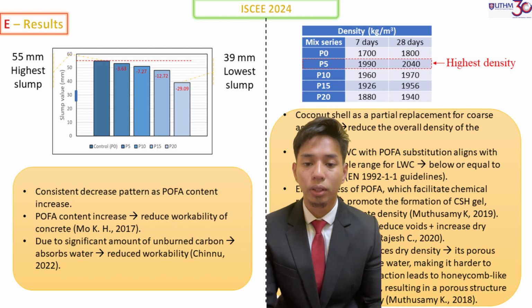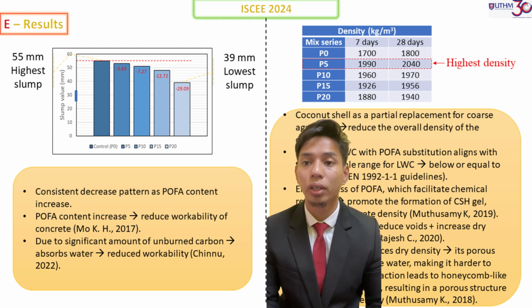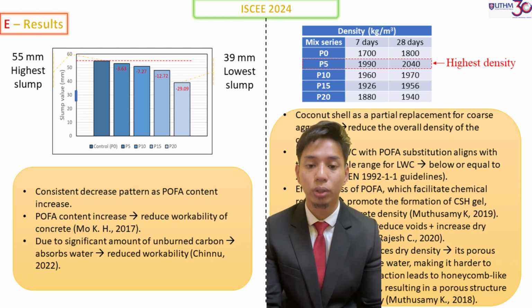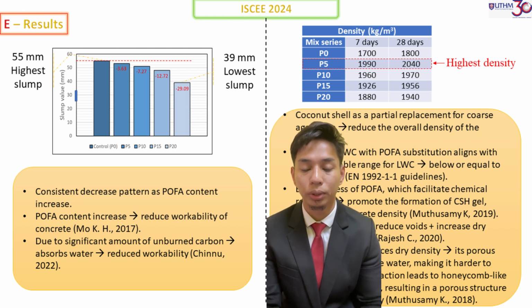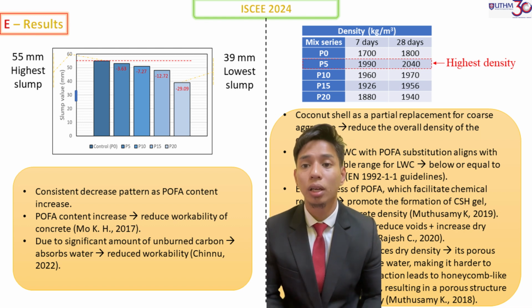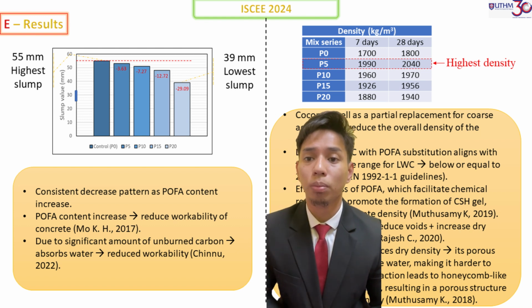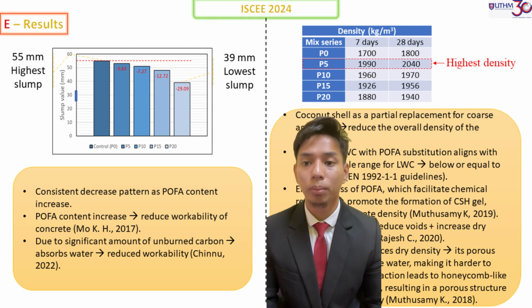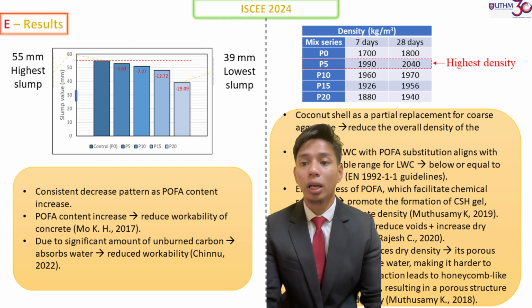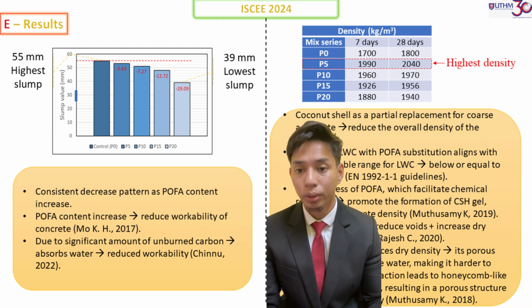So this is the result for the slump test. The highest slump recorded is 55 mm and belongs to the P0, which is 0% of POFA replacement. And the lowest slump is recorded as 39 mm and it belongs to the P20, which is the highest replacement of POFA, 20%. So a consistent decrease pattern is shown in the graph as POFA content increases. So the POFA content increase will reduce the workability of concrete. This is due to the significant amount of unburned carbon that will absorb water and reduce the workability.